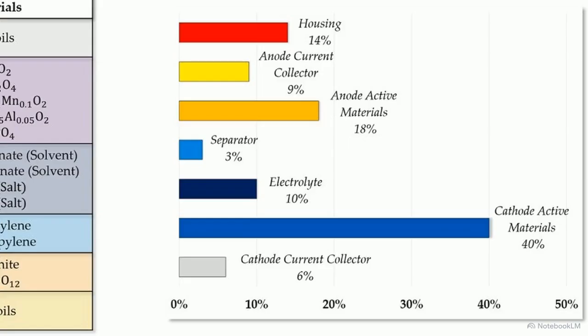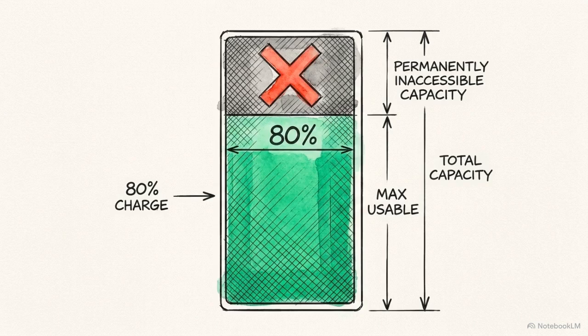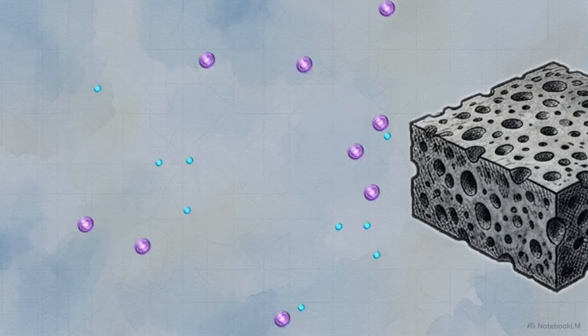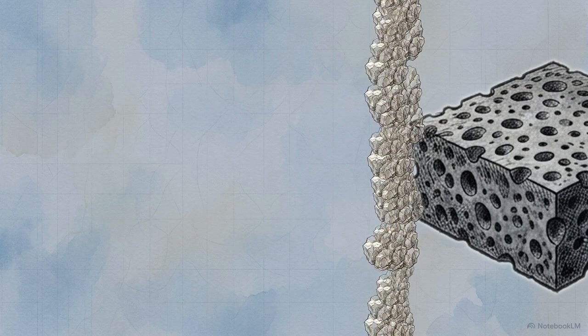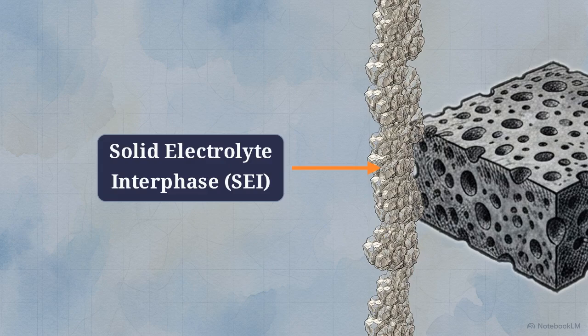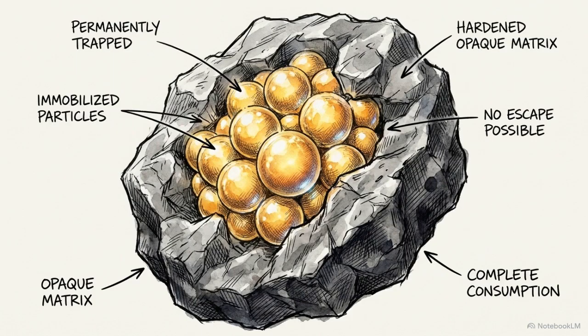This bar chart shows the weight distribution of a lithium-ion cell. The cathode and anode active materials account for 58% of the total weight. The remaining 42% comes from the housing, electrolyte, and current collectors, components that store exactly zero energy. Furthermore, operating cells never reach their theoretical capacity limits. During the very first charge, the electrolyte reacts with the electrodes to form a passivation layer called the solid electrolyte interphase. This irreversible chemical reaction permanently consumes a portion of the active lithium ions.